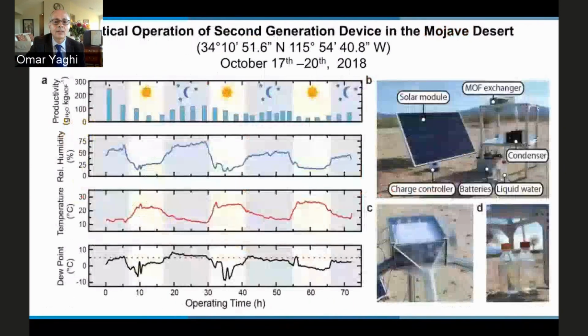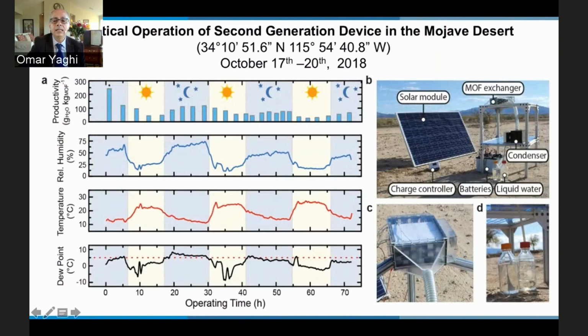Just for the interest of time, I'll zip through this. These are the results from the Mojave Desert, where we took 1 kilogram of MOF 303. In this case, we interfaced our device with a solar panel to allow us to have power to push air through the material. So this is a powered device that's going to allow us to do more than 1 cycle per day. So here you see the humidity in the Mojave Desert during the experiment. During the day, it goes down as low as 5%, 7% relative humidity. And during the night, you have higher humidity. Whether it's day or night, you are harvesting water.